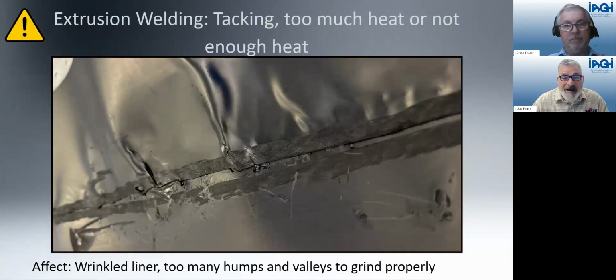Next slide, please. So extrusion welding, tacking, too much heat or not enough heat. This picture here demonstrates too much heat when you're tacking your liner together. You have excessive wrinkles and very bad grinding techniques. The grinding's not all the way to the edge, too many valleys and crevices to get the proper grinding when you're doing your extrusion. It's very problematic, and will lead to too many humps and valleys to grind properly and failed trial welds and failed destructs, of course.